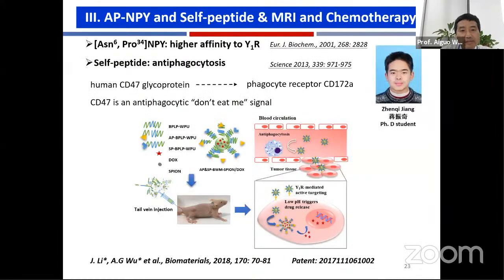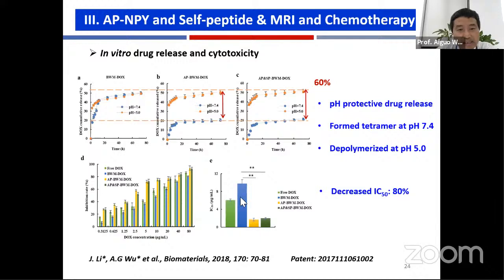And the third work I want to show you is where we use AP-NPY. At this time we made mutations of the NPY at sites 6 and 34 to get higher affinity to Y1 receptors. And also we want to avoid phagocytosis and use a self-peptide to get immune escape. So here is the scheme for our research work, and we found this kind of system is a pH-responsive